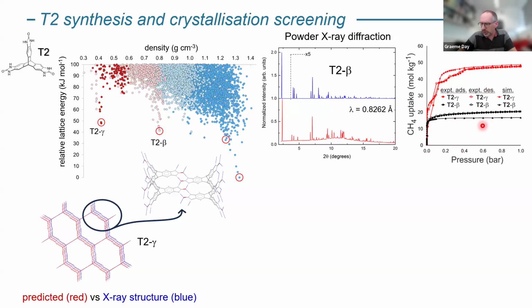And then if we go back to the predicted properties, so here methane uptake, these triangles here are simulated data. For here, that gamma polymorph, this one here, and here in black for one of the other polymorphs, this beta one, which is also porous, but less porous than this one. And then these other lines, data points, are now experimental because we've managed to make the material, and you can see good agreement. So that means that we've gone from predicting from just molecular structure to crystal structure and properties, and we're getting this all quite accurately. So we've predicted the methane uptake for these different polymorphs fairly accurately. So that's the success story for CSP.